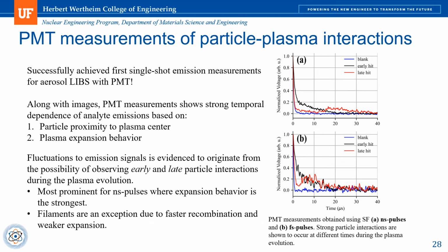You're seeing the produced plasma in air following the laser ablation interacting with the particles in the plume. So the expanding laser plasma is really your sampling method, and that's where you're getting your signal from. And the PMT measurements really showed that we could isolate the kind of rare cases where we got a hit early on in time, i.e.